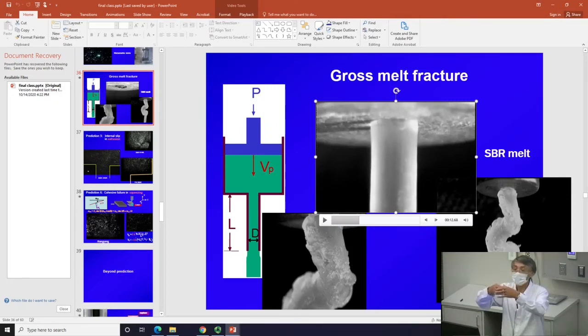Remember, it has a diameter of d. When it comes out, it can become much bigger, the extrudate. That's called swell. Look at this part. Didn't swell at all, and also smooth. Because this material is already resting in the die for a long while, the effect of the entry is not there, because it's already forgotten. But whatever is coming new, of course, sees the effect of the entry, and that's the rest.